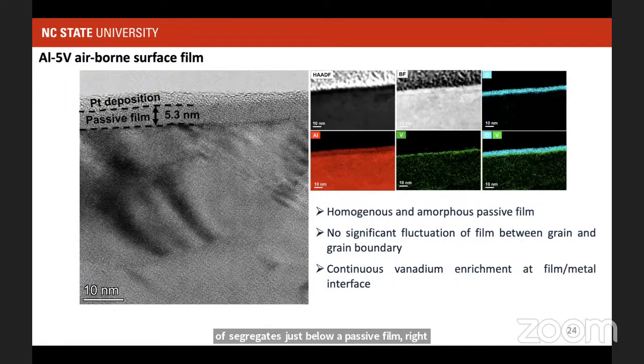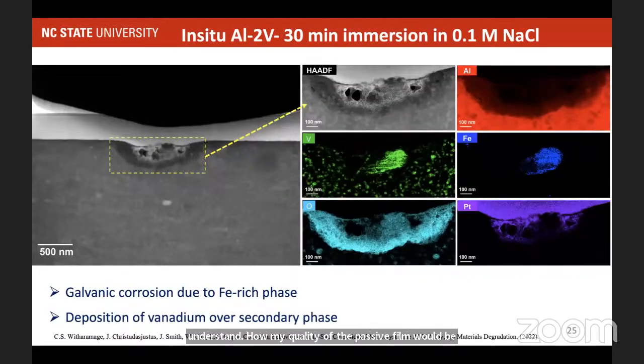Our initial hypothesis was something different. We initially thought that you would make an exclusive vanadium oxide layer and that would prevent corrosion. So that wasn't the case, but you at least have the segregation of vanadium, and based on that we further tried to understand how good the quality of the passive film would be, and we understood quite a lot. Probably we don't have time today to go into all the details. Another thing we learned was, and I'll talk a little bit about that later on.